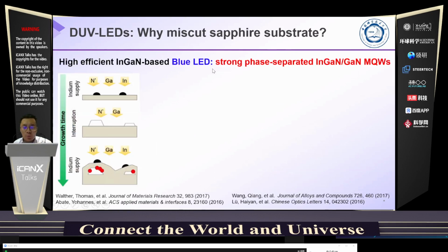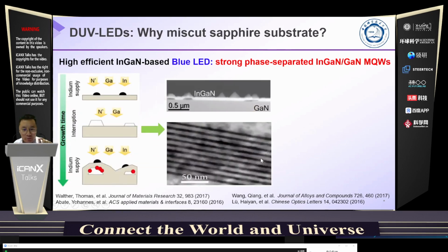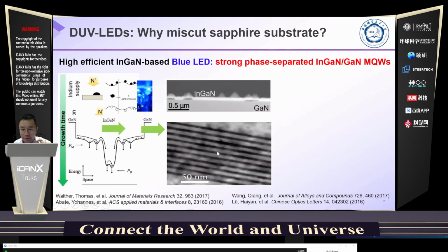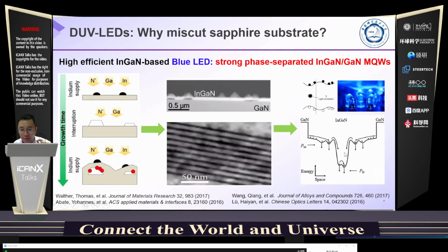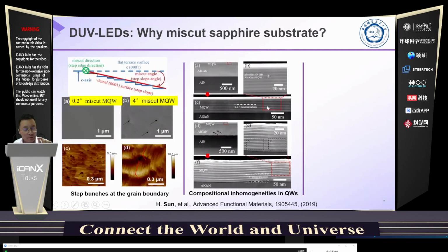For the blue LEDs, we have strong phase separation inside the indium gallium nitride quantum wells because the indium atom and the gallium atom have a very large atom size difference. As a result, when we create such quantum wells, we naturally create compositional inhomogeneity, and the carriers can be highly localized inside the quantum well. They cannot move around, so the only way is to recombine and generate blue light. But for AlGaN thin films, aluminum and gallium atoms have similar size. The only thing we can create is a very flat quantum well, as you see here. But we introduce a miscut sapphire substrate, as we show here.